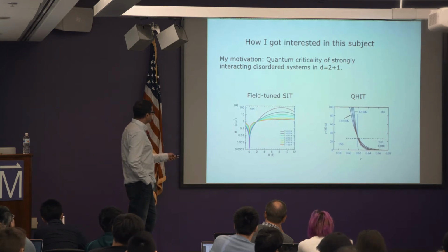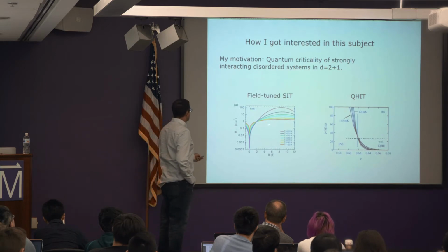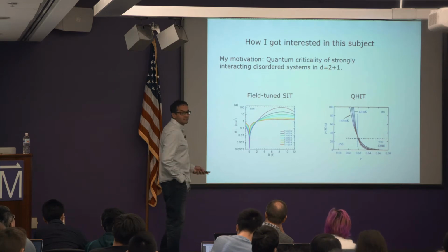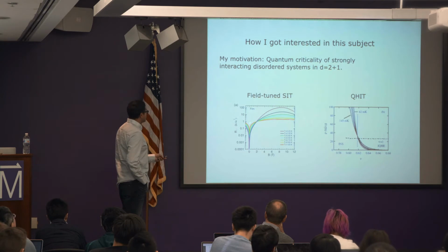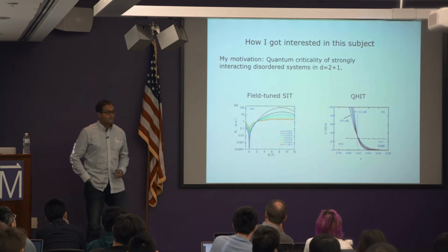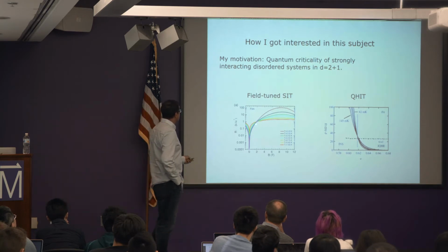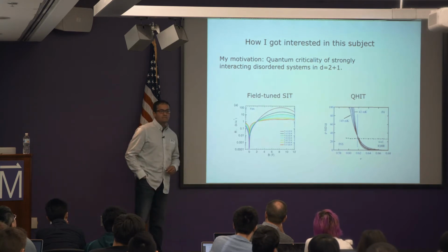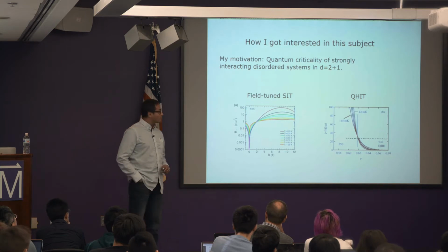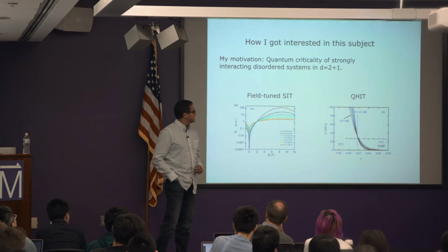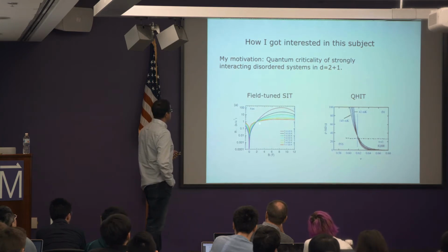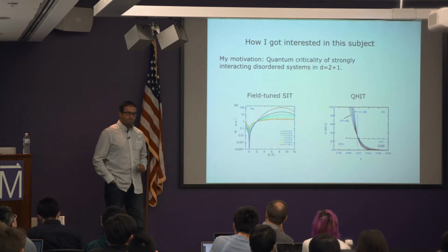So on this side, at high magnetic fields, let's see, the other way around. As temperature decreases, the resistance increases. Sorry. And that's the insulating behavior. And on this side, as temperature decreases, the resistance decreases, and that's the superconductor. Okay? And where these isotherms cross, the resistance seems to be universal, and roughly the quantum of resistance of particles with charge 2e. This is the superconductor to insulator transition.